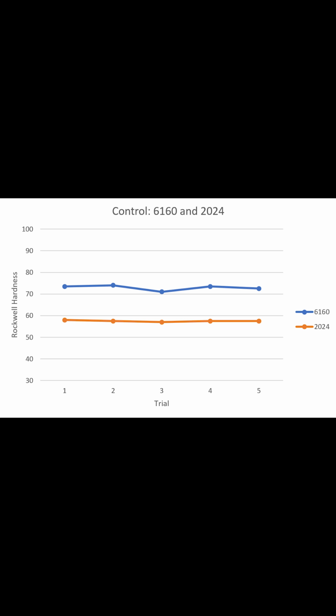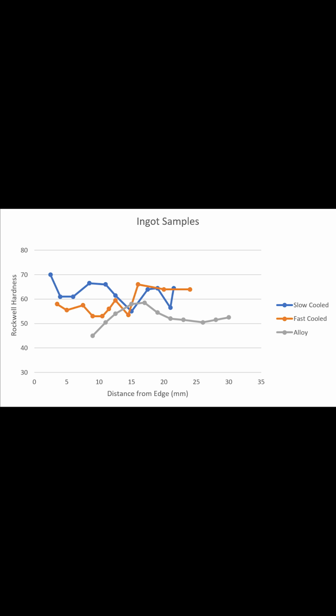The slow-cooled ingot had a higher average hardness rating than the fast-cooled ingot. The fast-cooled ingot developed a consistent trend as we moved closer to the center, which can be attributed to a more consistent grain size. Though we saw these trends in the slow and fast-cooled samples, there were a lot of outliers and a high standard deviation.